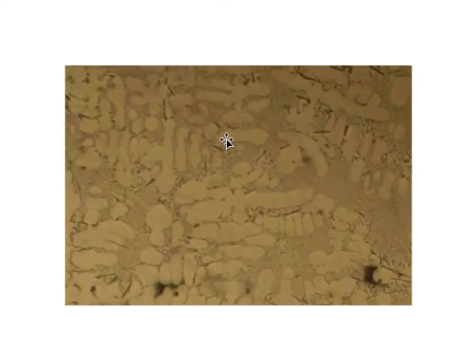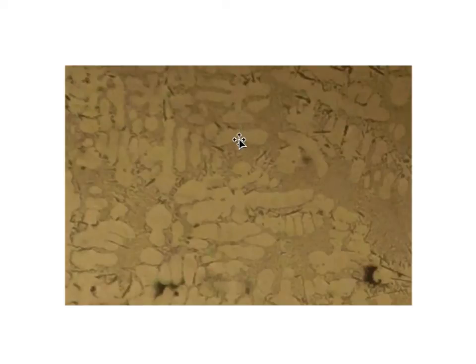Here we see a realistic microscopy view of this structure. First we focus and move around to get an overview — we can also see pores discussed before. Looking more closely at the structure, we see two features: the light phase is the aluminum phase, and the slightly darker areas are the eutectic areas. Especially notable is the shape of the aluminum phase — it's called dendritic structure, very typical of primary precipitation in metallic alloys. These dendrites grew in the two-phase region between the liquidus and eutectic temperatures, while the areas in between were liquid and then solidified into eutectic structure.